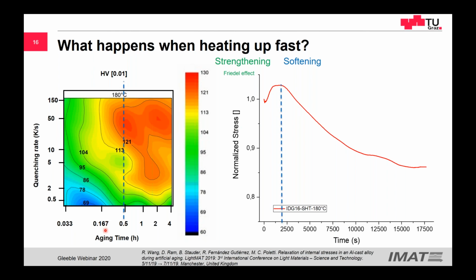And if we just take a look at the hardness curves here in 3D, we can see that we need half an hour. Please forget about the quenching rate. Let's take a very fast quenching rate. We need half an hour to reach the peak, which means this is more or less also what we see here, half an hour to reach the peak of precipitation, the strengthening peak. So this was very interesting. We use different machines, and since we have different processes and different heating rates, then we have different processes in our material, in this case the precipitation kinetics, and these produce different relaxation curves.